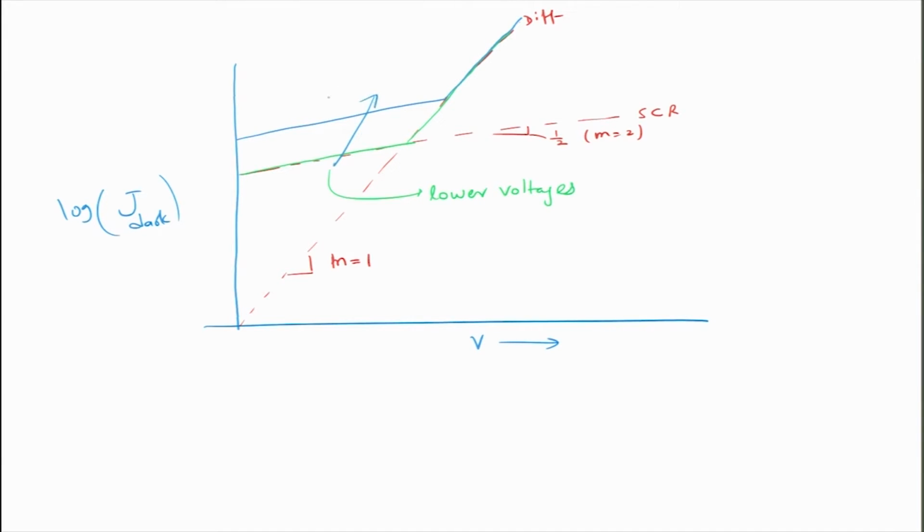So, this will go up if you decrease the carrier lifetime. When the carrier lifetime reduces, of course recombination is larger. As a result, recombination current dominates over the diffusion current. So basically your dark current will also be dominated by recombination rather than the diffusion current.